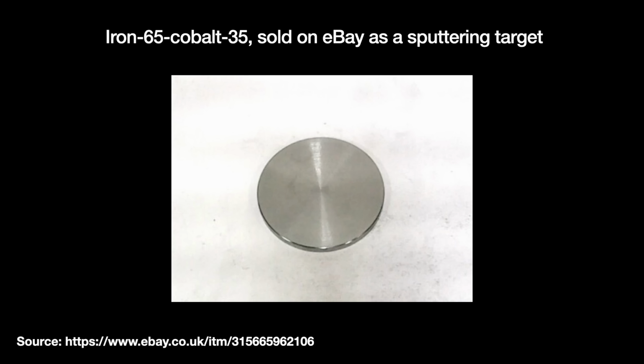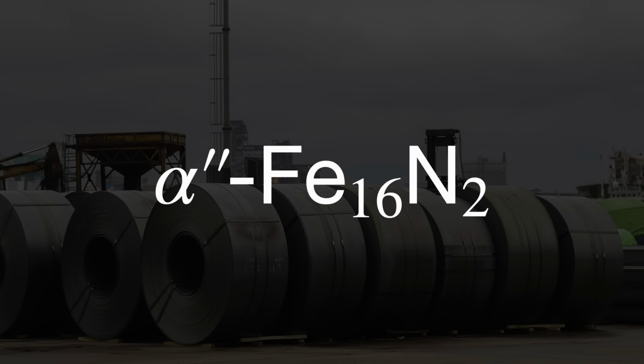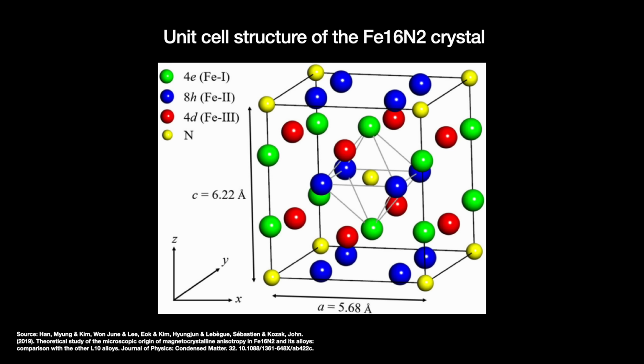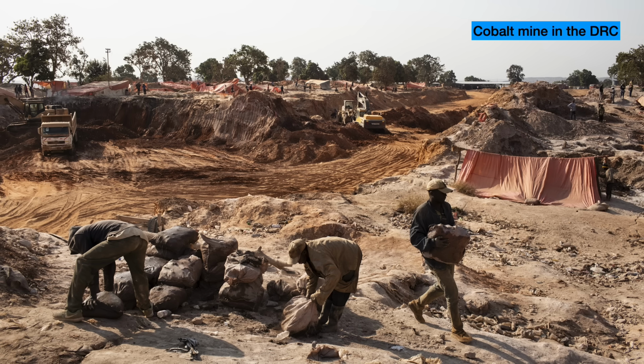The iron films contained a mixture of plain alpha iron and a phase of iron nitride called alpha double prime Fe16N2. This name refers to a specific type of iron crystal with nitrogen atoms modifying its structure. The crazy thing is that the average magnetic moment seemed to be about 3 Bohr magneton per iron atom, far higher than ordinary iron's 2.2 Bohr magneton per atom. Imagine that. Takahashi immediately dreamt of discovering a new permanent magnet made of iron and elements from the air with no dirty and expensive cobalt necessary. But first he had to confirm this new finding.